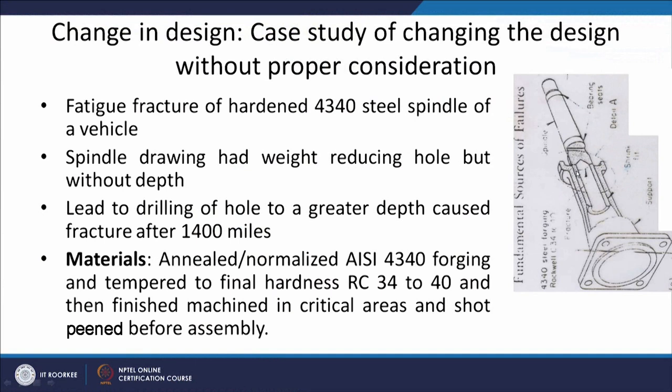This is the case study where, due to an unintentional change in design — drilling a hole of greater depth — it led to premature failure of the spindle during service. The case study is related to fatigue fracture of a hardened AISI 4340 steel spindle of a vehicle. The spindle drawing had a weight-reducing hole, but the dimension was unintentionally left unspecified. In one of the cases, the hole was drilled to greater depth, causing the failure of the spindle after 1400 miles.